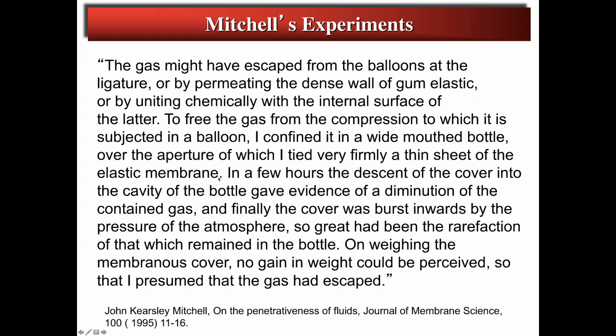He had put hydrogen in it, and in a few hours the cover descended into the cavity of the bottle. That is, if you have this bottle sitting out in air, filled with hydrogen, and at the mouth or top of the bottle is a thin membrane of essentially what we would call today natural rubber, the hydrogen will diffuse or permeate across that membrane faster than air gases can permeate in the opposite direction.